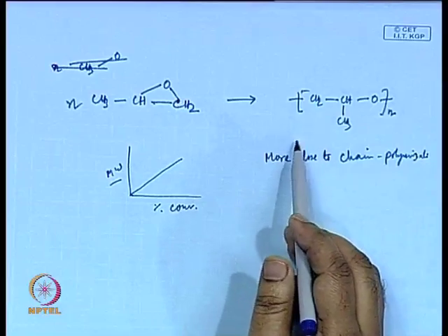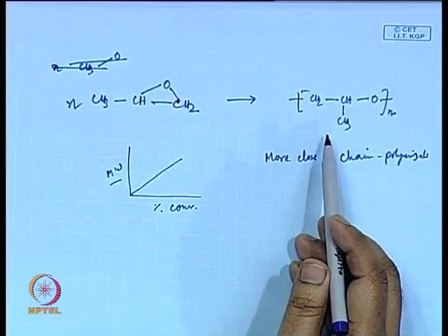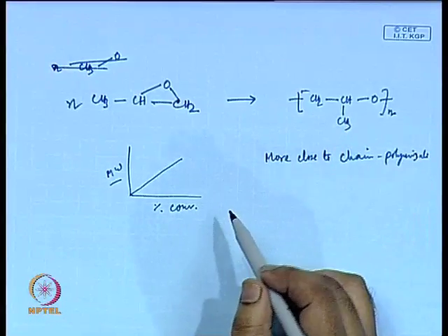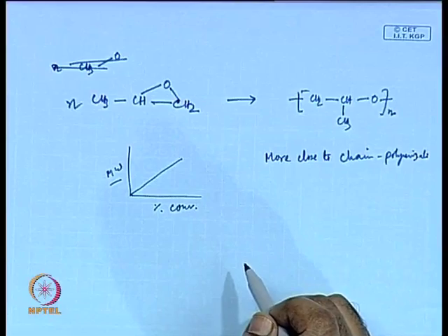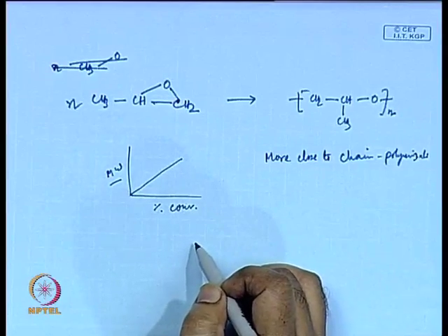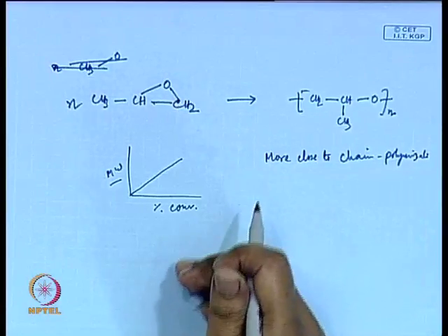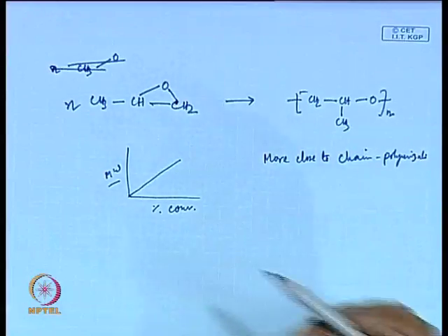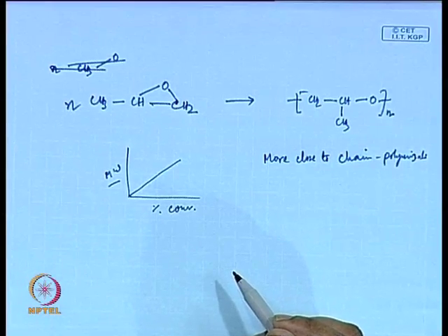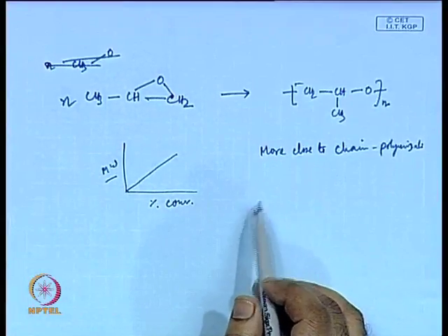So, this type of ring opening polymer, by structure you may confuse with step growth polymers, but actually from the mechanism, the way it is synthesized, this is more close to a chain polymerization of this type than a step growth polymer, where the polymers are formed stepwise, dimer, trimer, tetramer and so on. In this case the formation happens by addition of monomers towards the chain ends. More examples of such can be given where this classification is not completely unambiguous.